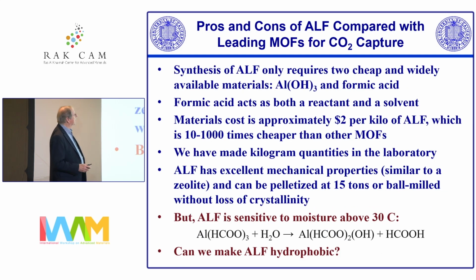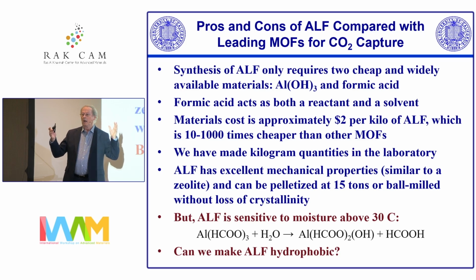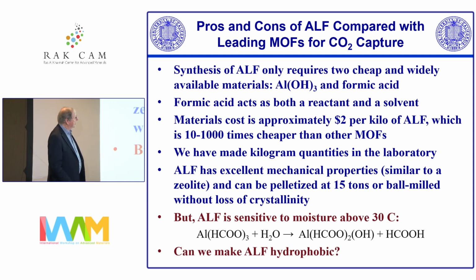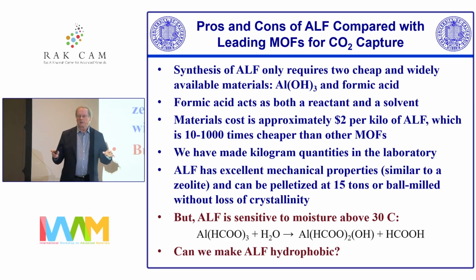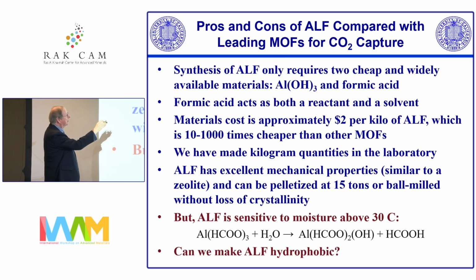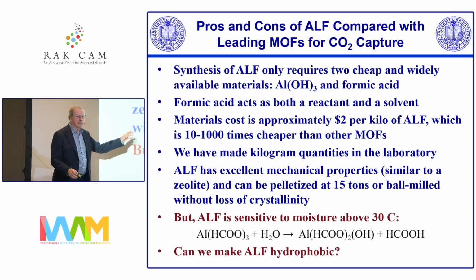So just at this point, what are the pros and cons of the ALF? Aluminum formate just requires formic acid and aluminum hydroxide. And they're roughly $1 a kilo each. But of course, if you have a kilo of aluminum hydroxide and 3 kilos of formic acid, you basically get 4 kilos of ALF. And so we reckon, when I made this slide, we thought we could make it for a materials cost of about $2 a kilo. And we now know that we can do it significantly cheaper than that. If you compare it with most other MOFs, it's a minimum 10 times cheaper, and in many cases, maybe as much as 1,000 times cheaper. And you can make kilograms of this in the lab.